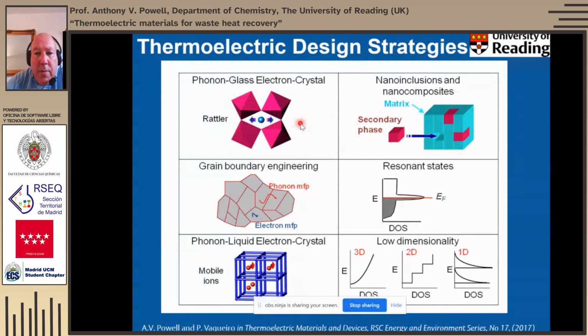Another way of influencing that thermal conductivity is essentially by creating interfaces, and that can be done by introducing what are called nano-inclusions into some matrix. So there's a series of materials Mercouri Kanatzidis developed called the LAST phases. They've got nano-inclusions within what is essentially a lead telluride matrix, or indeed introducing a second phase into that matrix, and then we get phonon scattering at the interfaces between the two phases.